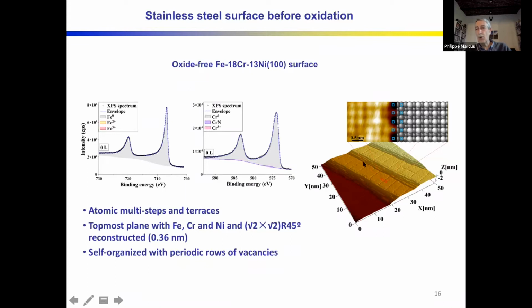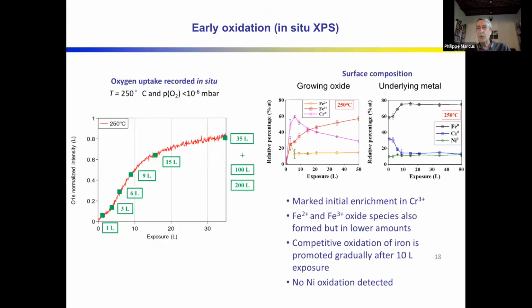There is a network of vacancies. You can see that these vacancies are aligned in well-defined directions. So now with such a very clean and well-defined surface, we can look at very early oxidation stages, and we can look at oxidation as a function of exposure.